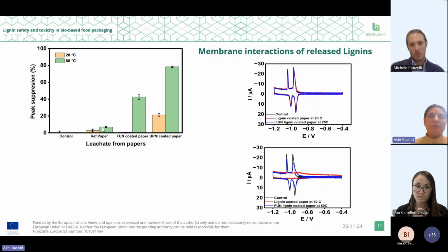From the reference paper, which is the uncoated paper, we can see that the peak suppressions are very insignificant, less than 10%. It can be used as a very good control for the lignin coated papers.